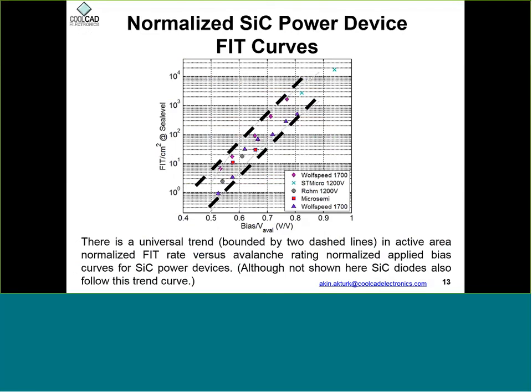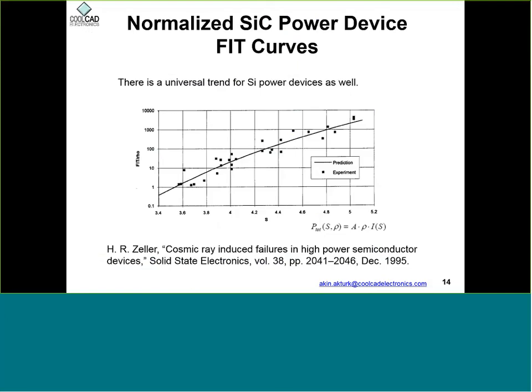So I briefly talked about this normalized silicon carbide power device failure rate. So this failure rate per area versus bias normalized by avalanche rating. So the question is, is this unique to silicon carbide? And it is not. So the same thing is observed in silicon too. So irrespective of what kind of silicon power device you have, there is a way to convert that failure rate so that all failure rates collapse onto one curve.